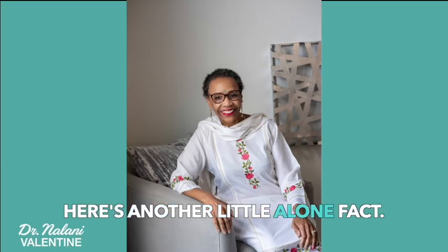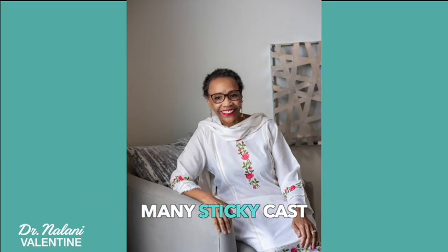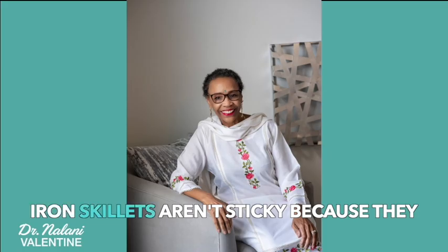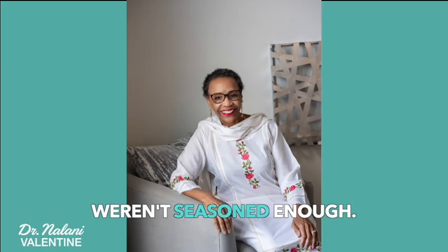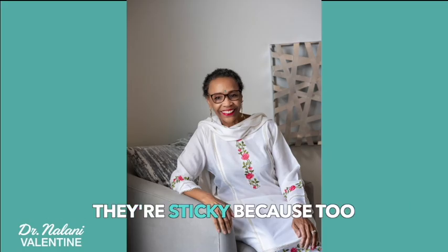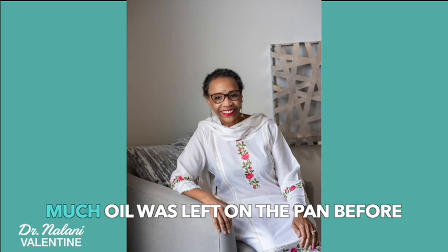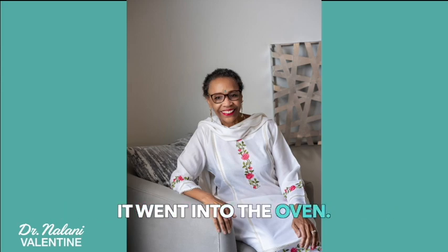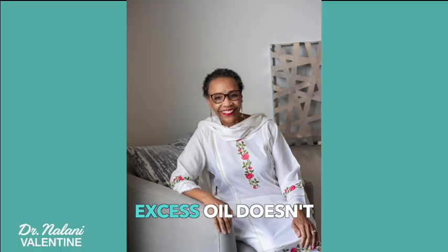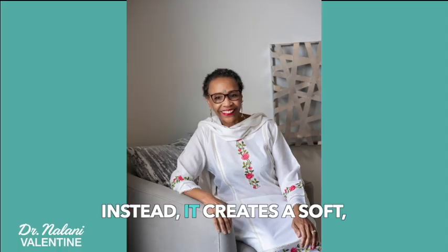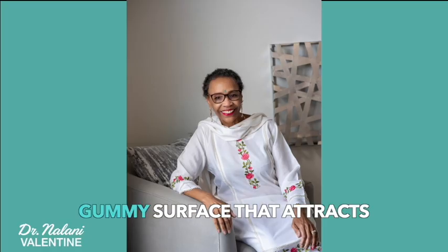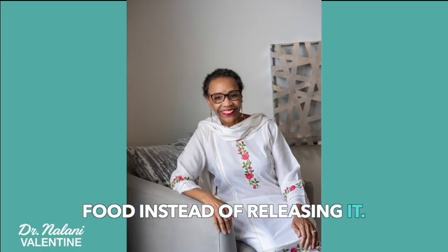Here's another little known fact. Many sticky cast iron skillets aren't sticky because they weren't seasoned enough. They're sticky because too much oil was left on the pan before it went into the oven. Excess oil doesn't fully polymerize. Instead, it creates a soft, gummy surface that attracts food instead of releasing it.